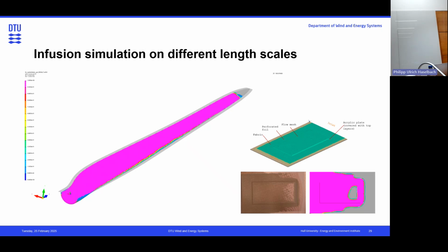And also with inserts. When you look at big wind turbine blades, usually they're not only made out of glass fibers any longer, but they have pultruded, precast carbon inserts that they put around. And of course, when you put these planks into the fabrics that should be impregnated, it's like a blockage effect, and you really would like to understand it, so that you get a really good impregnation of the entire material. This is what we tested on smaller scale, where we built a kind of root section or half part of it and modeled it, and then compared to our experiments, and we feel very confident, so that we went to the next step and tried a full scale infusion.